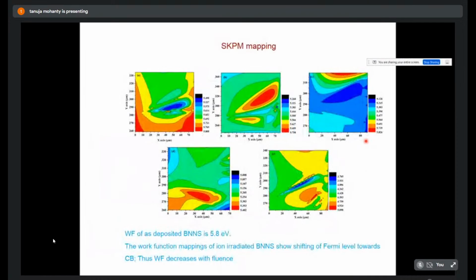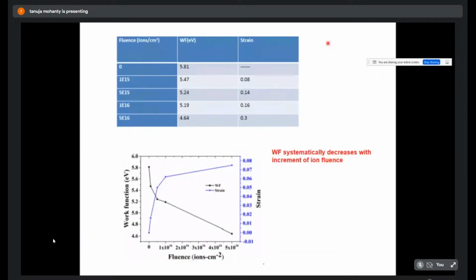So we have similarly done the SKPM imaging, and there also the WF was found to be 5.8. But what we have found is that the strain is calculated here like this, and we have plotted the WF value and the compressive strain here. So the work function value and the strain go in inverse ways; they are related.